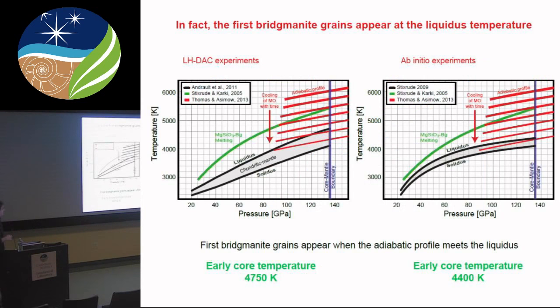But in fact, if you look more carefully at the phase diagram, this temperature is already too high. Because what really happens if you want to make a layer of material, you don't have the MgSiO3 alone. You have a mixture of phases with the ferropericlase, the Bridgmanite, and the calcium perovskite. So you will crystallize at the liquidus. There's been a big discussion about where is the liquidus of the pyrolitic mantle, the chondritic mantle, and I'm not going to go too far in those discussions.